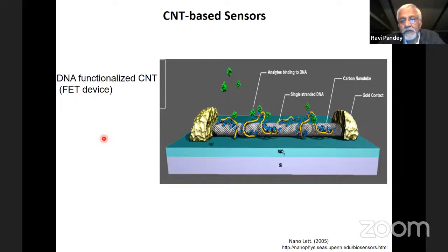So this again is a cartoon, and we have worked extensively on the so-called DNA functionalized carbon nanotube. As we know, if you look at the curved, tubular nanotube surface, the px, py orbitals of carbon are bonded in plane, but the pz orbital is floating around. And it forms what we call the pi electron cloud. So in order to make these carbon nanotubes active for sensing, you have to functionalize them. The best way is with DNA, because DNA, as you remember, has 4 nucleotide bases: guanine, adenine, thymine, and cytosine. These are nothing but carbon rings.